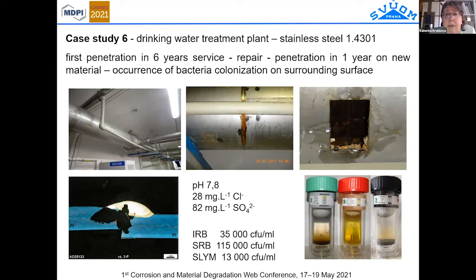Case study 6 was a drinking water treatment plant, also stainless steel. It was interesting because the first penetration occurred after 6 years of service. The pipeline was repaired, and in this repaired place the penetration occurred after only 1 year of the new material. That means that if the pipeline is new, it takes a relatively long time for the bacteria to colonize the surface. But if only a local repair is made, this place is very quickly colonized by bacteria from the other inner surface of the pipeline. Here we can identify a lot of bacteria, both sulfur and iron reducing bacteria.